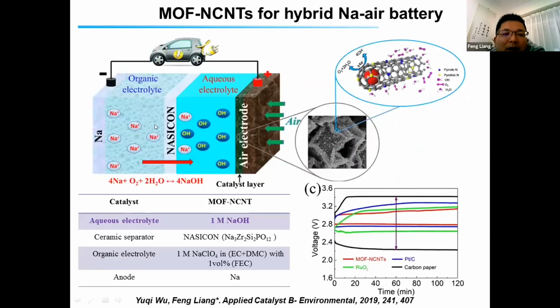So in order to solve this challenge, we already did a lot of work. Firstly, we prepared the MOF-derived nitrogen-doped carbon nanotube as the catalyst for the hybrid sodium battery. So this is the structure of our catalyst. It can be used as an OER and ORR bifunctional catalyst. And the result indicates that our catalyst has better performance than the platinum carbon and the ruthenium oxide. So this is our work about the catalyst for the hybrid sodium battery.